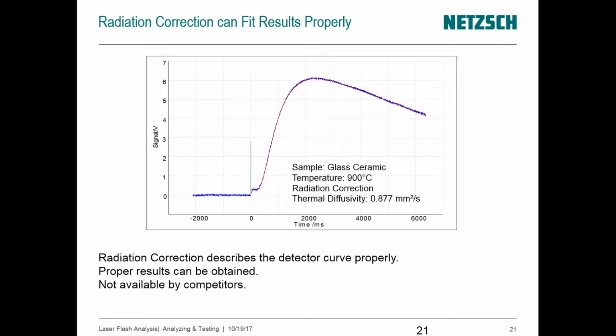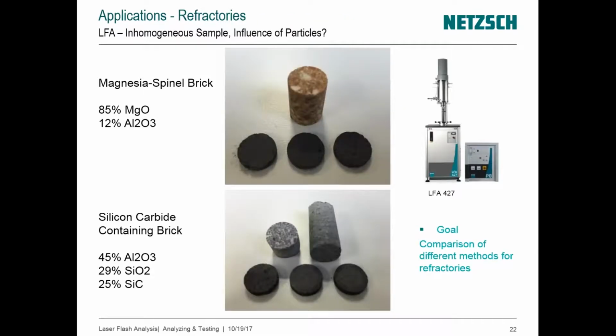So the takeaway is that when transparent samples are being tested, there are appropriate models geared towards that, and that's very important when it comes to ceramics. Now, in terms of application data, we will be looking at various materials. First, we're looking at bricks, as you see here. Those bricks tend to have many components, they are not necessarily isotropic. They are particles of different sizes, different natures. In the first case it would be a mixture of magnesium oxide and alumina. I'm sorry, in the second case, it would be a mixture of alumina, silica, and silicon carbide. So these are fairly non-homogeneous materials, and we will go into the sequence of testing them and show what we get.